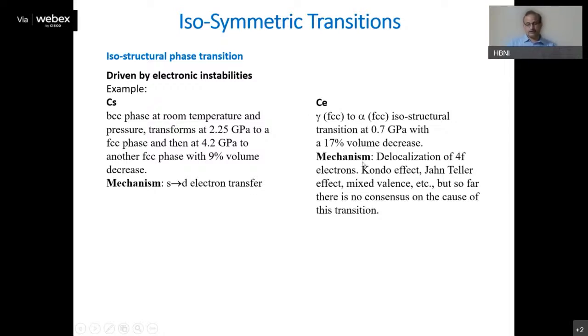Similarly, in case of cerium, you see there is a 17% volume drop at a pressure of 0.7 GPa. And here again, there is an electronic instability that gives rise to the phase transition. There are many explanations. The first one was based on the 4f electron, so 4f electrons basically delocalize. This was the earliest theory given to describe this phase transition. But there are many more theories based on the Kondo effect, Jahn-Teller, mixed valence, which try to describe this phase transition. Even still there are papers coming which try to describe this phase; it is not clearly understood.